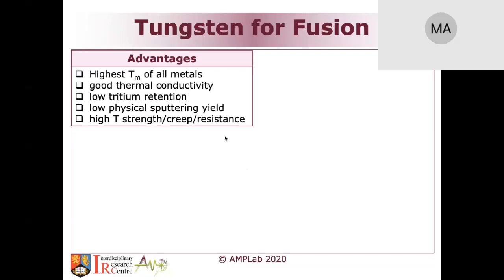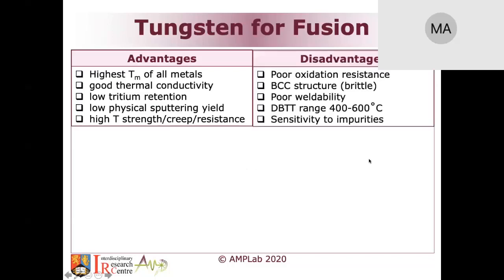But on the negative side, in general, as I showed you, it has poor oxidation resistance. So this might not be an issue when you are doing a fusion case. It's not too bad, because in fusion we don't have that much oxygen anyway. In general, it's a BCC structure, a body-centered cubic structure. And we know that body-centered cubic materials are in general very brittle. They also have very, very poor weldability. And this is essentially an important criterion to know whether we can use it for additive manufacturing or not. If you can't weld it, it's highly unlikely that you can use additive manufacturing to make it.